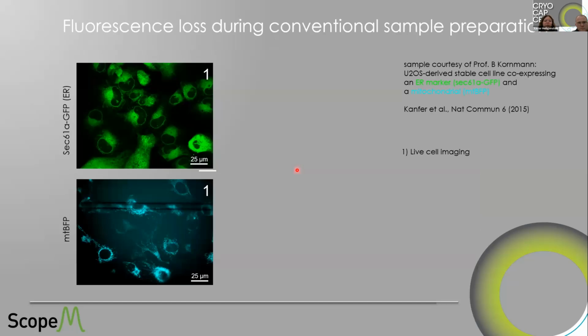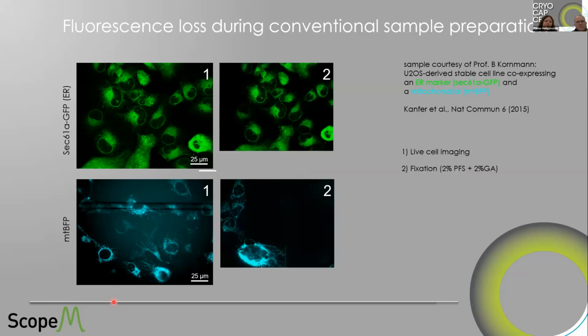Now, what also was very important for us was to figure out at some point where exactly we lose the fluorescence. We have heard all the theory by Xavier earlier on, and now this is how it looks basically in images. This was done with a microfluidic device on a light microscope, where we could exchange the medium directly on the light microscope and basically watch at which step we actually lose the fluorescence. So here we have a GFP signal and a BFP signal in the same cell line. This is still live, and then we start the fixation. And even if we have a high concentration of glutaraldehyde, which is said to have an autofluorescence, it didn't disturb us too much. We still have nice fluorescence.